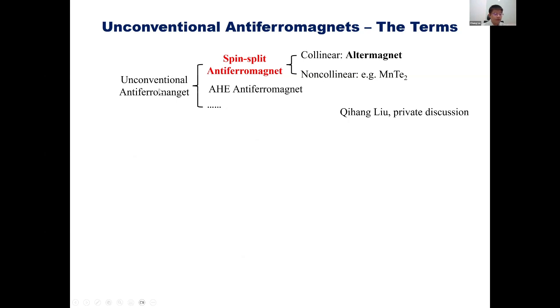So now we examine the terms that often appear in the field of unconventional antiferromagnets. In the past years, we started to recognize that some of the antiferromagnets exhibit properties that usually appear in ferromagnets instead of antiferromagnets, like the anomalous Hall effect and the spin splitting and so on. Here we loosely define the term unconventional antiferromagnet to be all the AFMs that show such unusual properties. Therefore, unconventional antiferromagnets include spin split antiferromagnets, the AHE antiferromagnets, and so on. The spin split antiferromagnets can be divided into two parts: the collinear Altermagnet and the non-collinear or even non-coplanar spin split antiferromagnets.